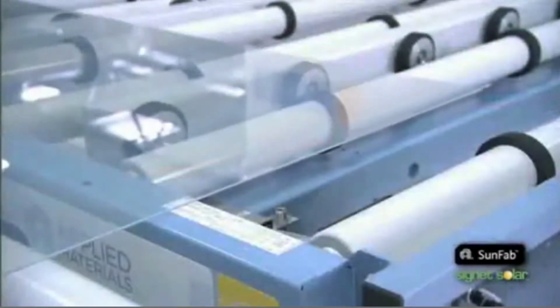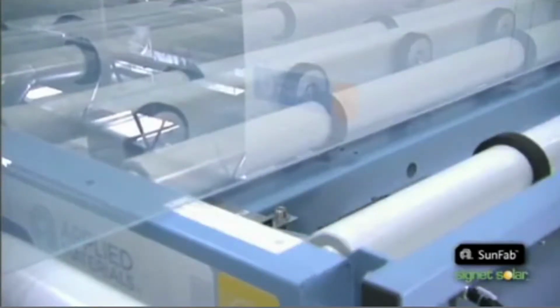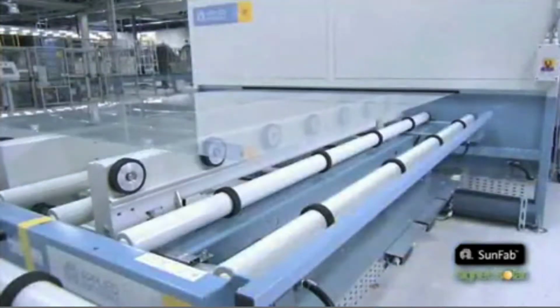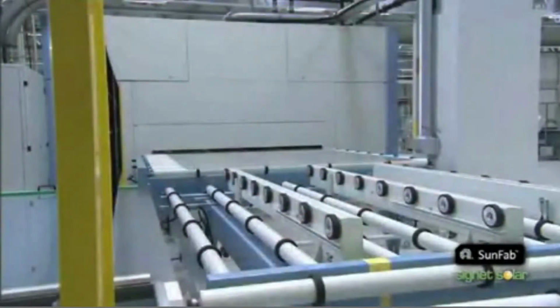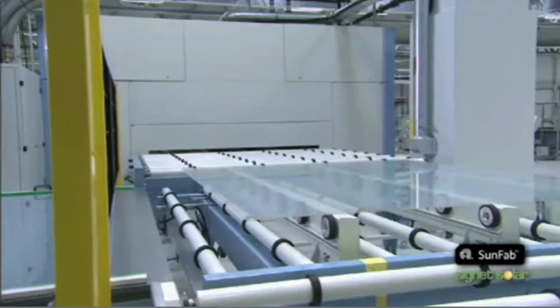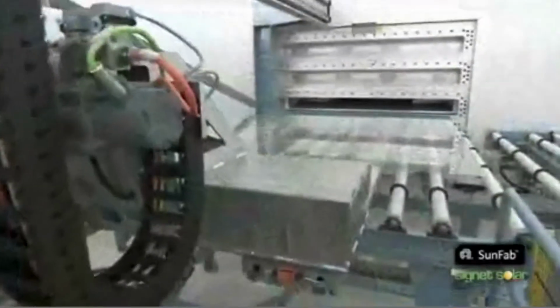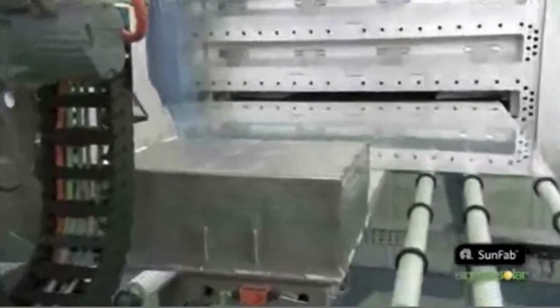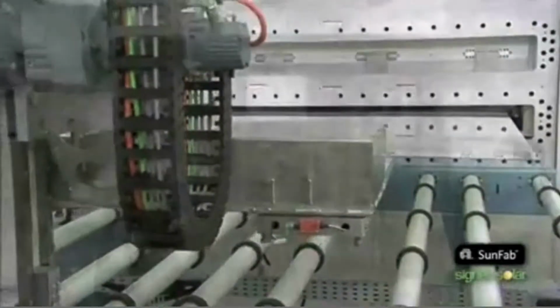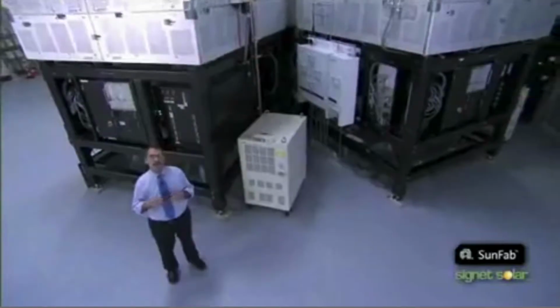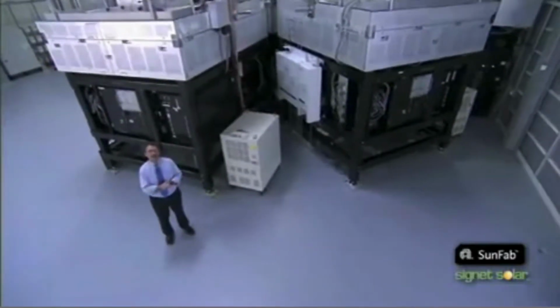The glass then enters a laser scribe where the P1 scribes of the front TCO layer are performed. We are now ready for the deposition of the silicon layers. The conveyor moves the substrate to the plasma-enhanced chemical vapor deposition chamber where the P-doped layer is deposited first. Several of these large PECVD systems are used, and in each a different type of layer, either P-doped, intrinsic or N-doped, is deposited. This is the glow discharge of the plasma in one of the chambers.